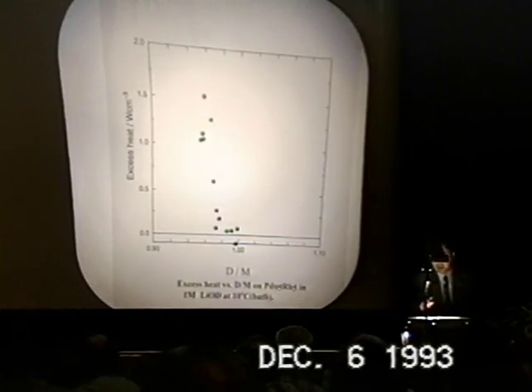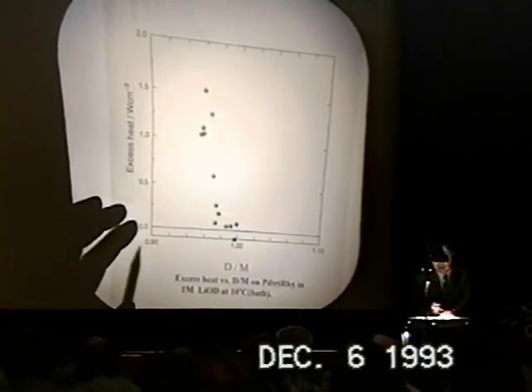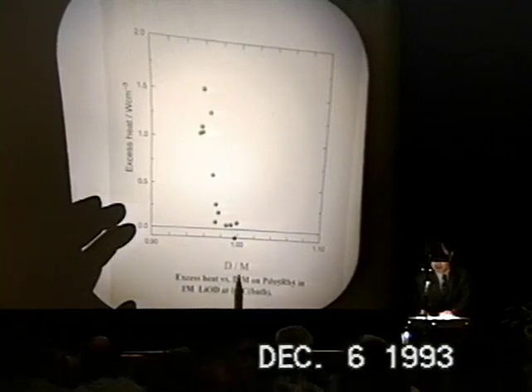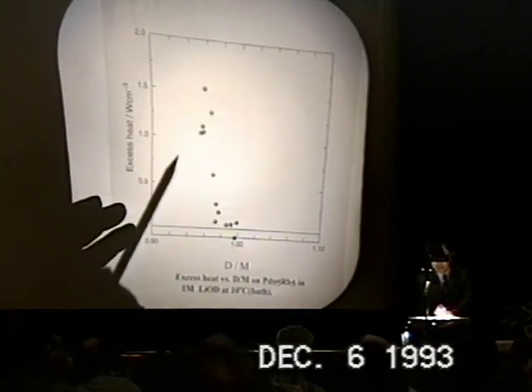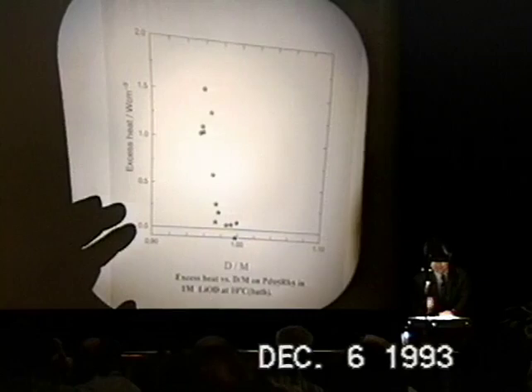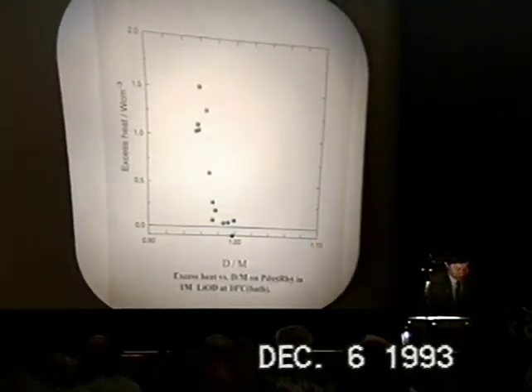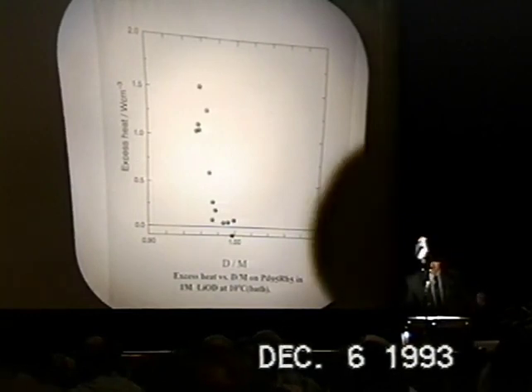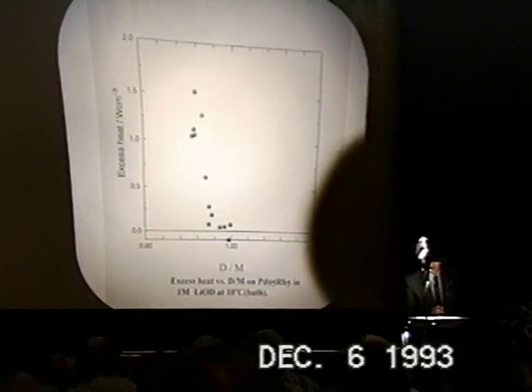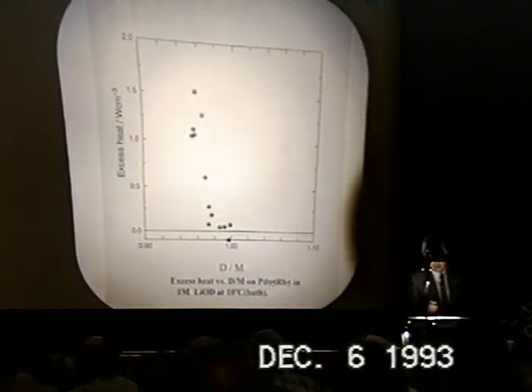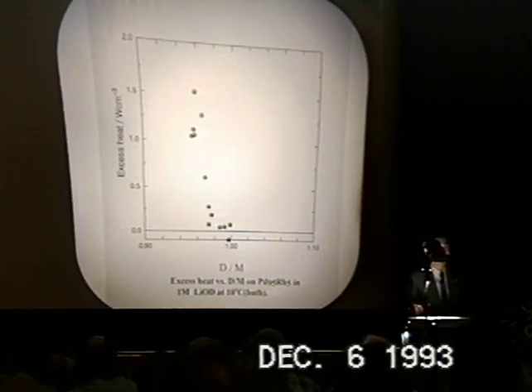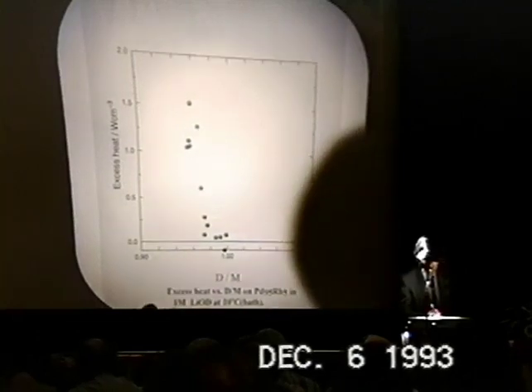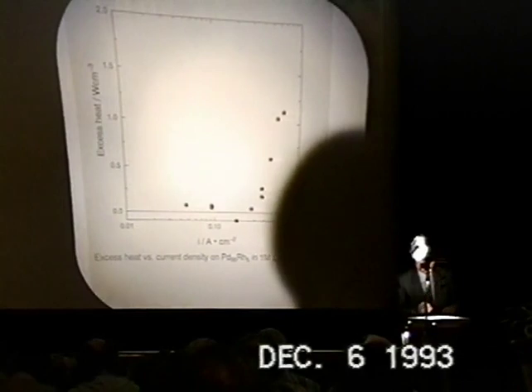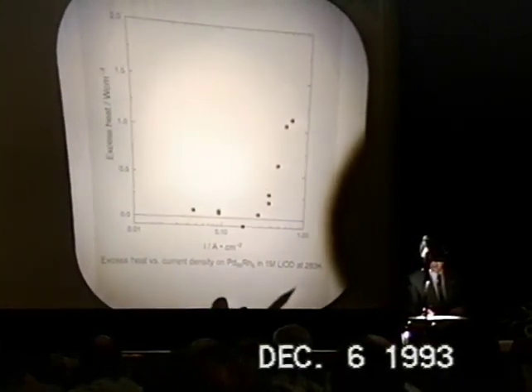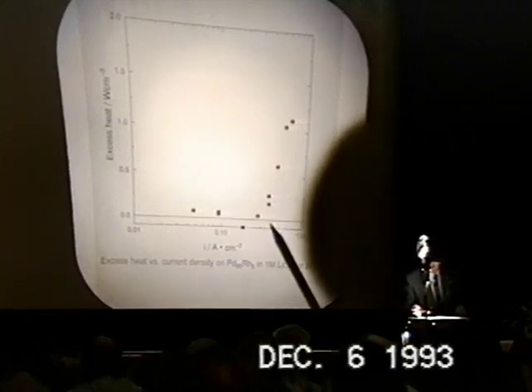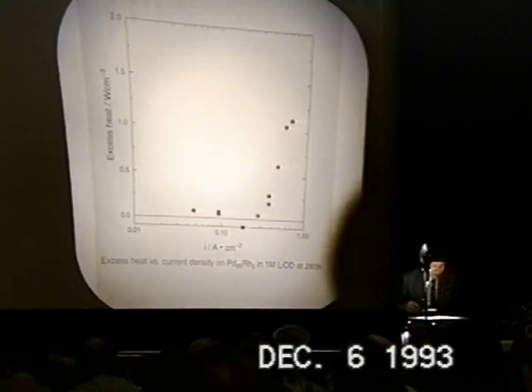This is more clear to show the actual dependence of excess heat as a function of D over M. So it decreases sharply in this region. Probably, I should say, this is very embarrassing data to show the decrease of excess heat at the region where it is not supposed to behave like this. But if we plot the same data as a function of current density, we have no problem to show the general increase of excess heat as a function of current density.